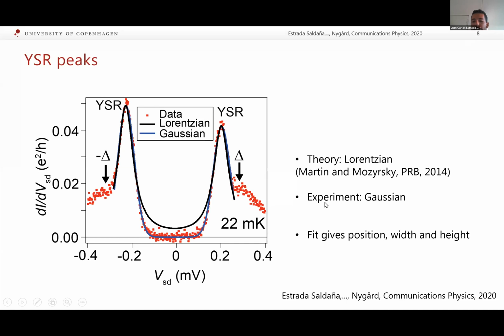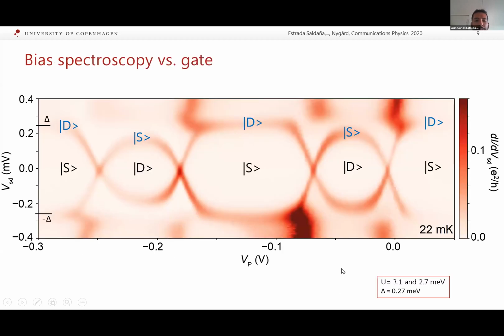And then we proceeded to fit with the sum of two Gaussians, and to our surprise, the peaks fit very well to the sum of two Gaussians. So we're going to use in the following this fit to extract the YSR peak position. We also extract the width and the height, but we won't talk about this today because of time. And you can see in our paper the results concerning the width and the height.